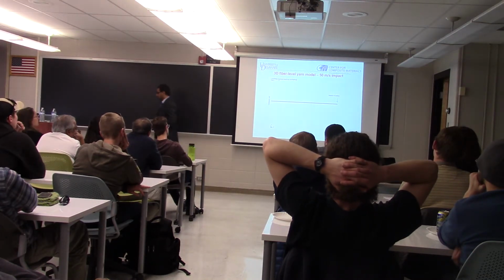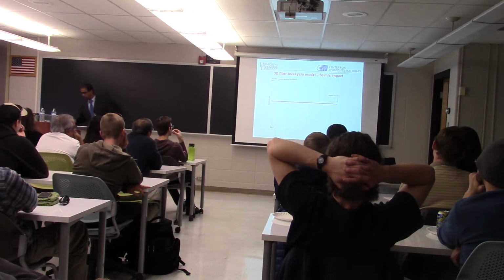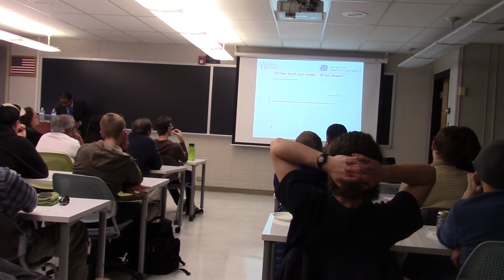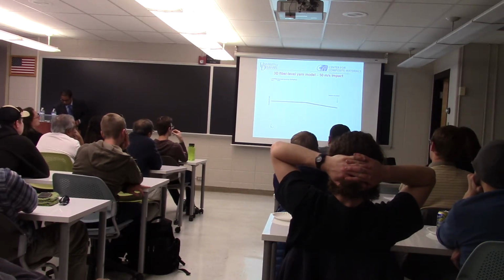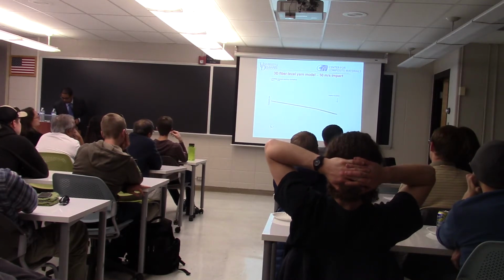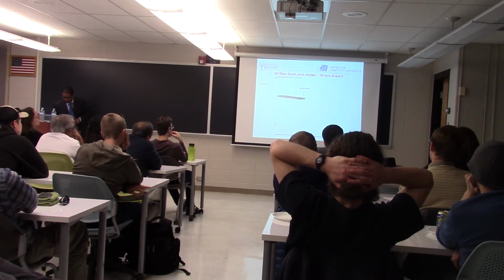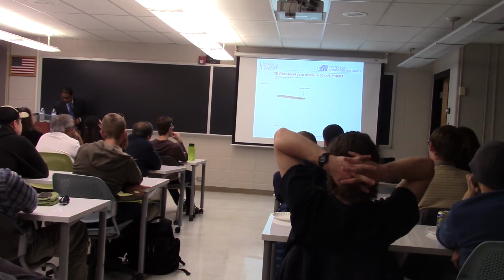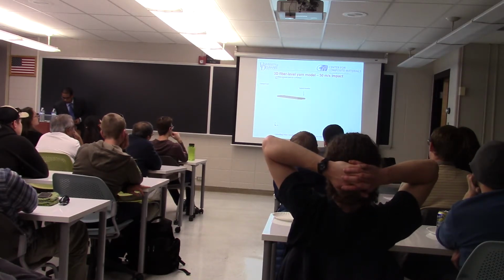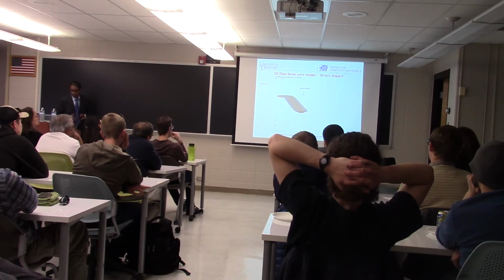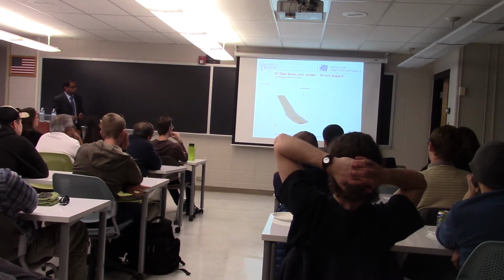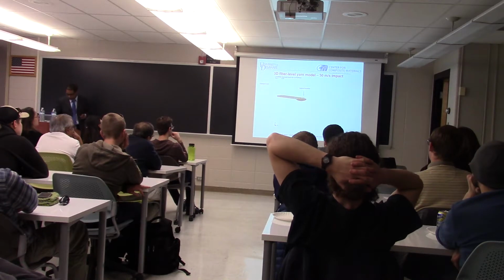So this is a movie at the long time scales. The transverse wave that I talked about initiates from the impact location and propagates to the clamp end, reflects, changes the particle velocity and returns to the impact location. And in addition to the transverse wave, we also see an additional spreading wave. It spreads the fibers to a large extent. This is due to the fiber-fiber contact.